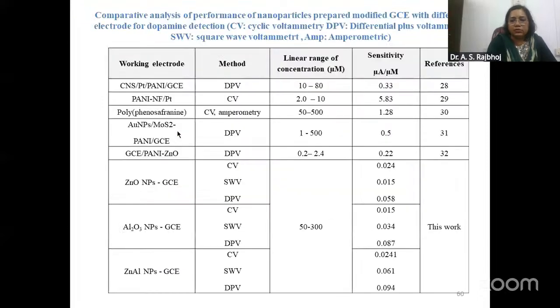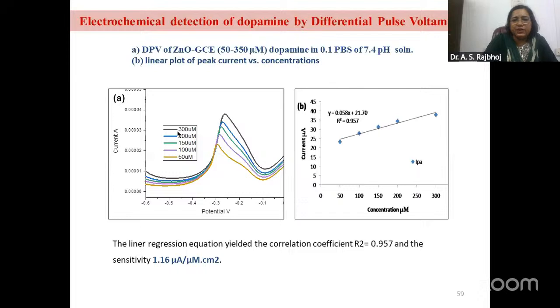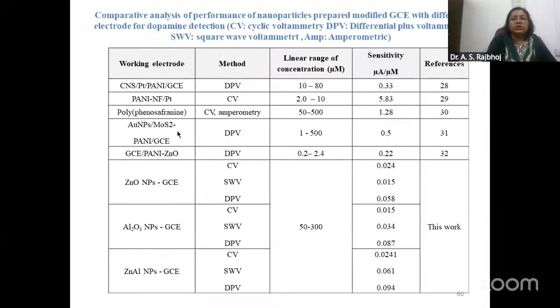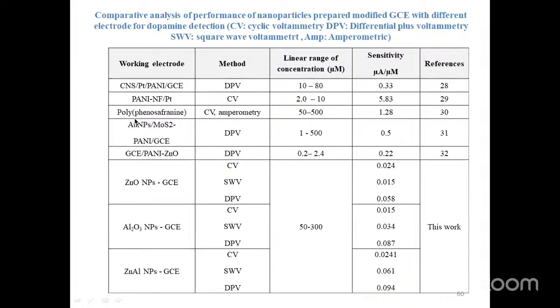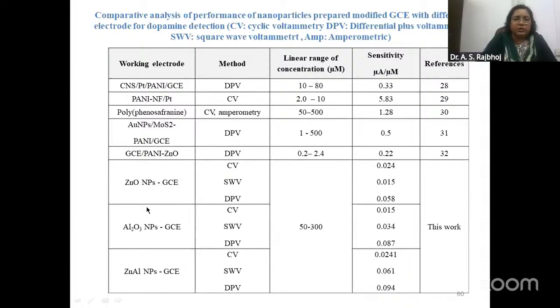Then here you can see the regression equation yielded the correlation, that is R2 equal to 0.957, and the sensitivity was found to be 1.16 microampere per micromolar centimeter square. Here you can see the first 4, 5 are from other work, that's our reference work, and the last 3 are our work.